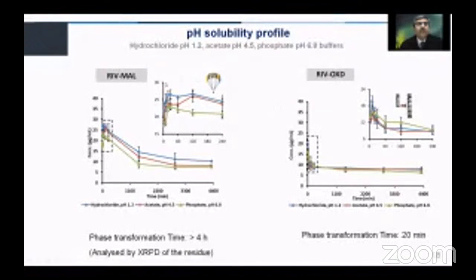The pH solubility profile of the malonic acid and oxalic acid co-crystals were evaluated. And a very important aspect that came out of this particular study was the phase transformation time, which was more than 4 hours for the malonic acid co-crystal, but it was only 20 minutes for the oxalic acid. This means that the solubility advantage that is going to be obtained from the malonic acid is going to be like a spring parachute effect, and the solubility is going to be maintained at a higher supersaturated level for biopharmaceutically relevant time frames. While in the case of the oxalic acid, the higher solubility that was obtained falls back to the lower solubility very, very quickly, and this is called as a spring effect.